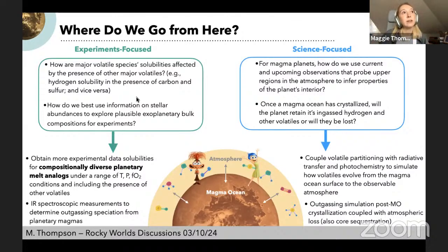If a particular law predicts that your solubility would just skyrocket, that's probably a problem. If it just plateaus, maybe then it's okay. Ultimately we need more experiments. For something like hydrogen, my understanding is it's really challenging when you get into several GPa, tens of GPa, especially because the hydrogen diffuses out really, really fast. So that quench process that I told you about is not fast enough, and your hydrogen escapes too fast, but hopefully we can get some more experiments that help us.